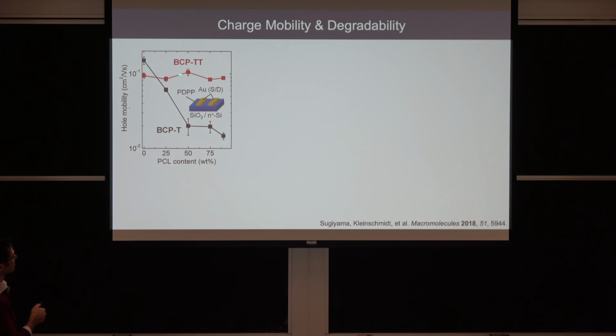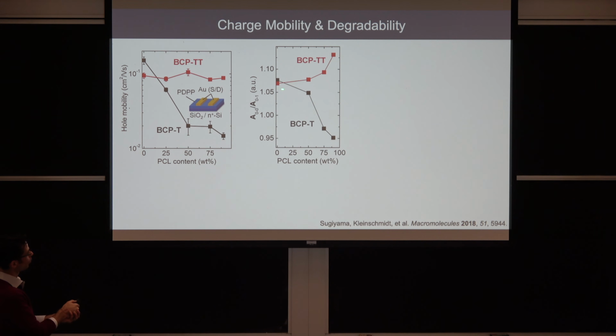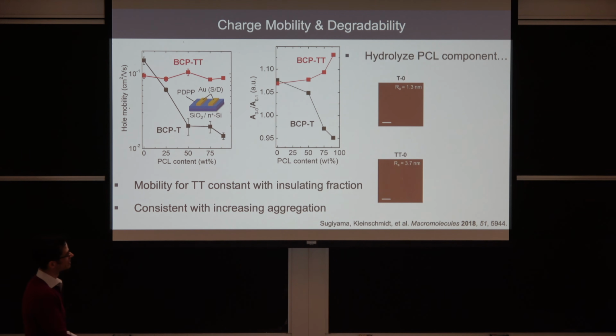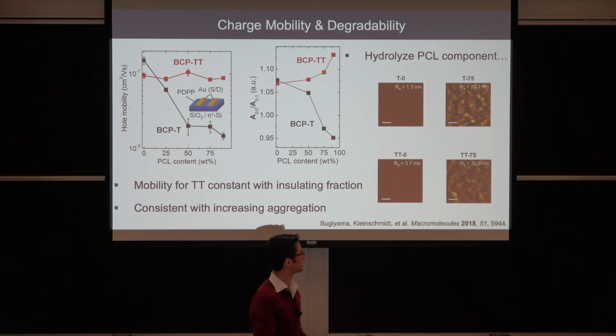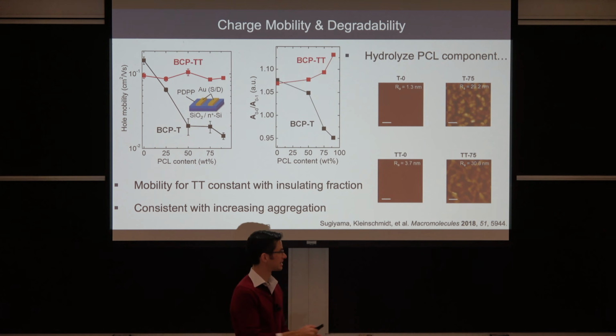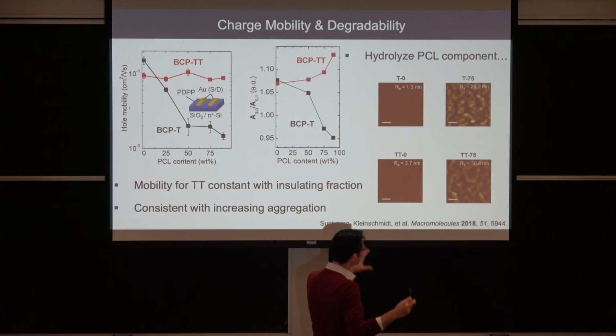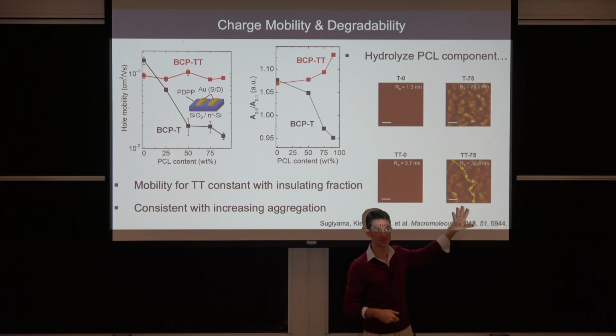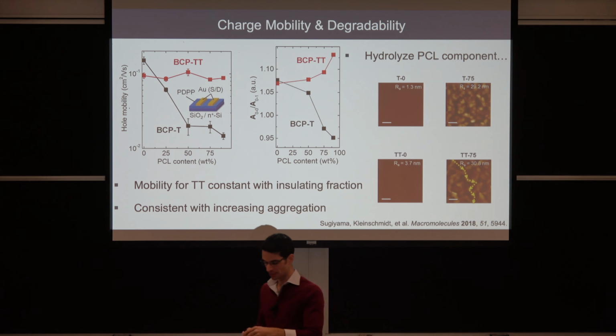So this is the charge carrier mobility of the material as a function of the amount of biodegradability. So as you increase the amount of biodegradable stuff, you'd expect the charge mobility to tank. But if you have the right comonomers in here, you can actually retain this charge carrier mobility. Now, if you plot the aggregation behavior, the order in the semiconducting regions actually increases, which is a good thing. And also, if you dissolve or hydrolyze the degradable segment and you look at this material, which is 75% of the biodegradable stuff, what's left over is the semiconducting stuff. And if you kind of squint your eyes, you can kind of see a percolated charge transport pathway here. So that was really encouraging.